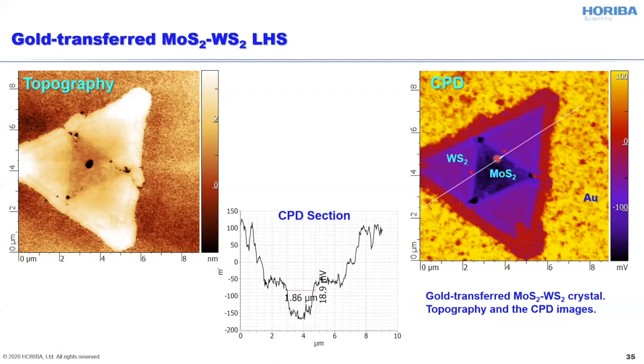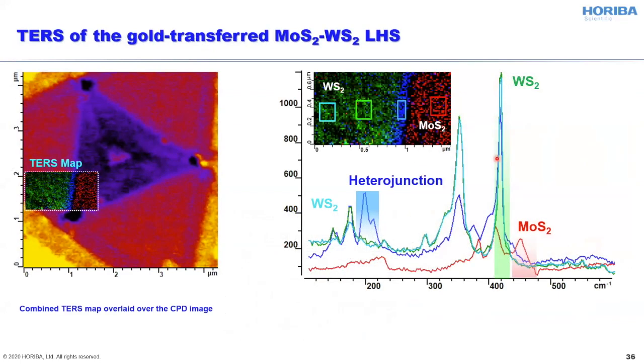So molybdenum disulfide core, tungsten disulfide shell. And when we ran the tip-enhanced Raman scattering map of this junction area, again, we observed the same spectral signature as we saw in samples that we discussed earlier. So appearance of this peak at around 200, 210 wave numbers in the transition area, which in the case of this specific crystal was about 100 nanometers. Another interesting observation that we made in this sample was the fact that the intensity of the peak at around 178 wave numbers was decreasing as we moved away from the junction line between the molybdenum disulfide and tungsten disulfide.